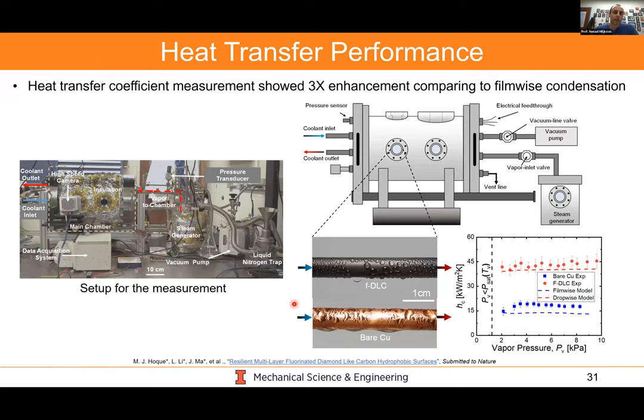We then go and measure the heat transfer performance. This is the chamber that we used in lab. This is nothing but a vacuum-compatible high-pressure chamber where we can mount samples, in this case, tubes. And we have coolant flow on the inside of tubes. We actually visualize the flow. And you can see down here, this is what condensation looks like on the FDLC tube, as well as comparison to the bare copper tube.